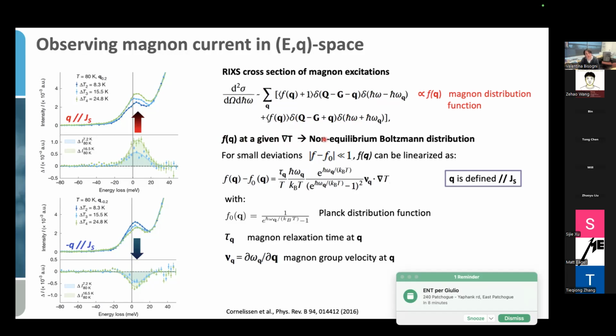To express this equation, we resort to the non-equilibrium Boltzmann distribution. A few hypotheses have to be introduced, and let's consider the linearized expression of the non-equilibrium Boltzmann distribution, since we are dealing with a small deviation from the equilibrium condition. Under such circumstances, we can express our magnon distribution function with this equation here, where I'm introducing a few parameters like tau q, the magnon relaxation time at a specific q. Then we have nu q, the magnon group velocity at a given q. And then we have the magnon frequency omega.